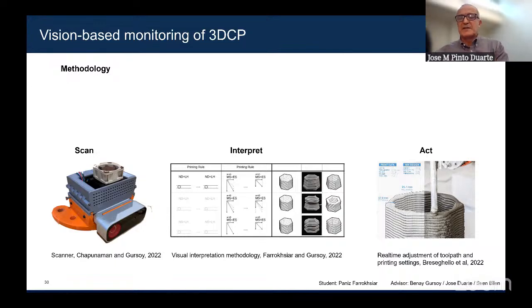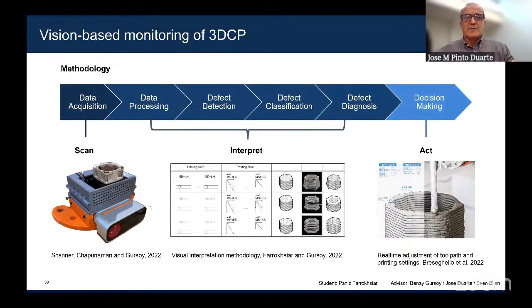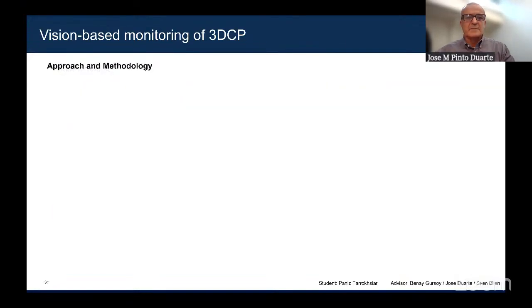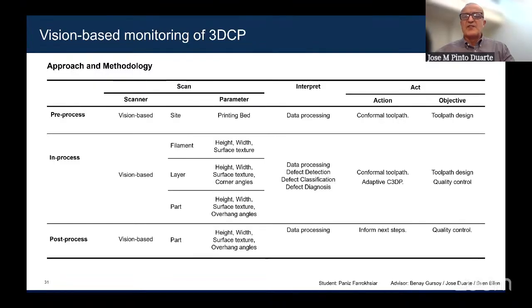So basically, we have 3 steps: scan, interpret what the camera sees, and then act to correct what's not going well. And this is how you can use the system, in a more elaborate way, for data acquisition, data processing, defect detection, defect classification, diagnosis, meaning finding out what might be causing the problem, and then deciding which action to take to counteract what's going on. With this, we can have very good control of the shape of the printing filament, and you can adjust the toolpath in real time to the changes detected during the printing process.